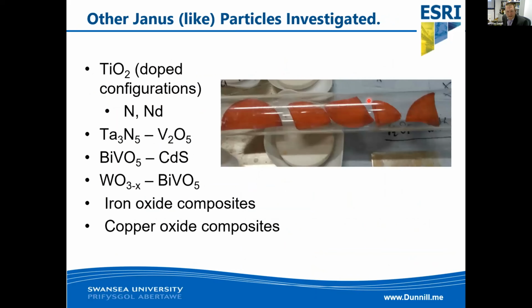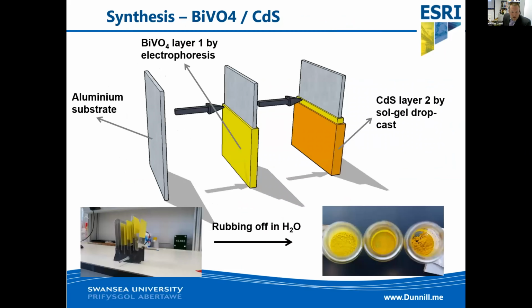So this work moves on. We can now look at Janus-like particles. Rather than just having titanium, we can actually start mixing various phases. We can dope individual sides. We can start putting nanoparticle islands on the top and bottom. And we can start picking hydrogen and oxygen catalysts to go with it. These red samples here are, of course, tantalum nitride, which is a beautiful material, but you can actually have that on top of vanadium oxide. We've done work, as you'll see in a minute, with bismuth vanadate and cadmium sulfide. We've done work with tungsten oxides in various forms and bismuth vanadates. Iron oxide composites and copper oxide composites are, of course, really interesting, as we've just heard from Adam as well. So the synthesis itself has huge amounts of potential to give you a lot of power.